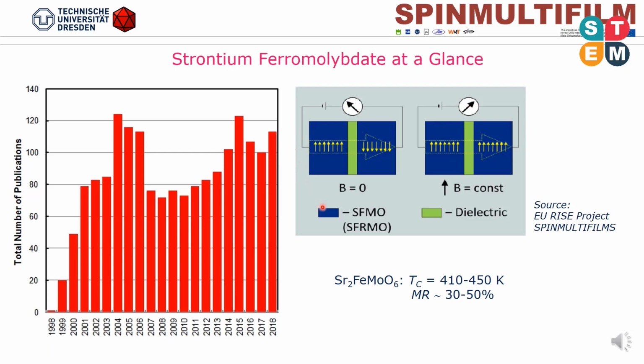Strontium ferromolybdate double perovskites are good candidates for magnetic electrode materials for room temperature spintronic applications because they present a half metallic character, that is a 100% spin polarization theoretically, a high Curie temperature. Note that ferromagnets should be operated in their ordered state below the Curie temperature. And the already mentioned low-field magnetoresistance.